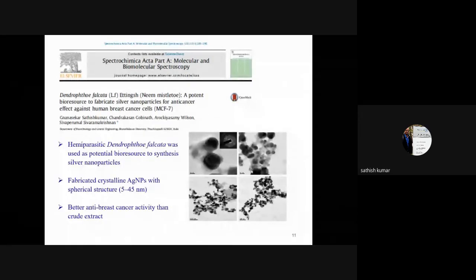In biogenic synthesis, not only the capping agent or the reducing agent plays a role. There are certain physiological conditions, the reaction parameters, that also play a major role in the size and the shape of the nanomaterials. So here we found that the synthesized silver nanoparticles were in the size range between 5 to 45 nanometer.